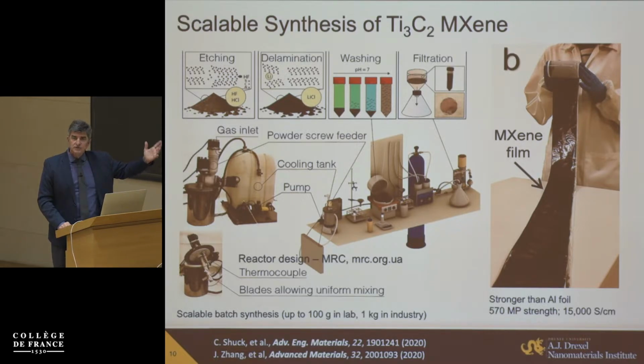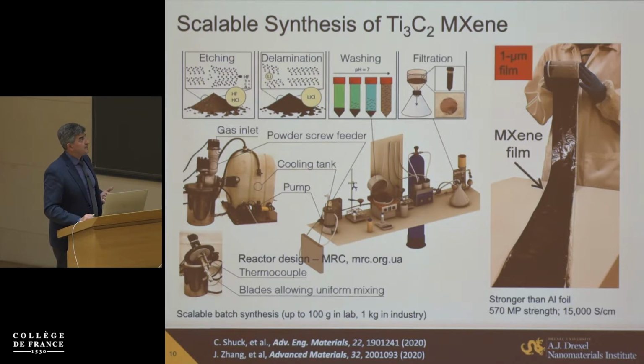So you basically imagine, Professor Tarascon was just talking about the contribution of various elements in batteries. Imagine you replace 70% of the copper that is in a battery, if I recall correctly the number on the pie chart, by a current collector which is 3 times thinner, 4 times lower density, so basically an order of magnitude lighter. Instead of 17% weight, you have, say, 2% weight contribution. It can by itself be attractive for battery applications here.